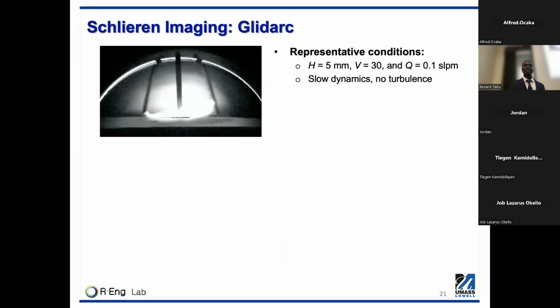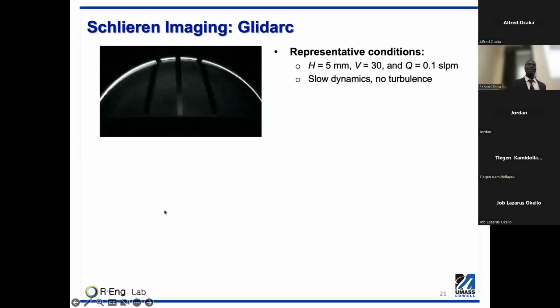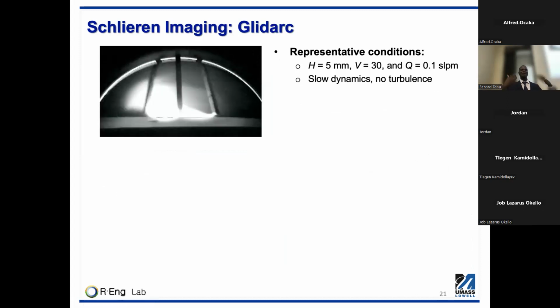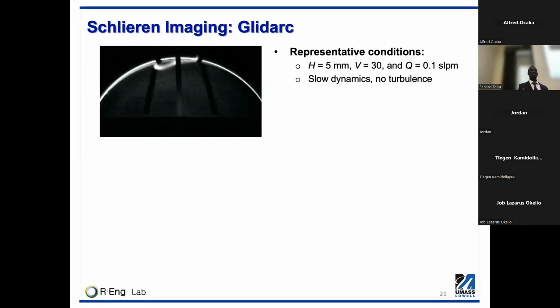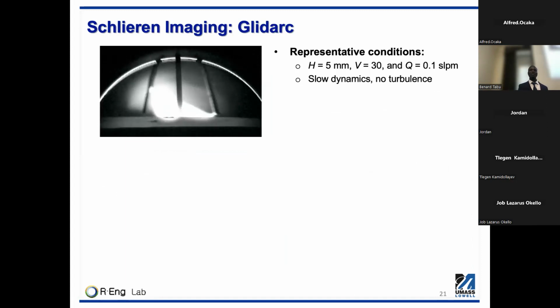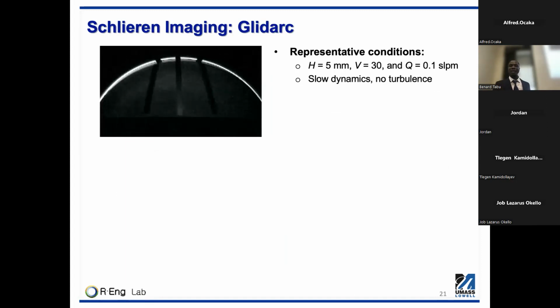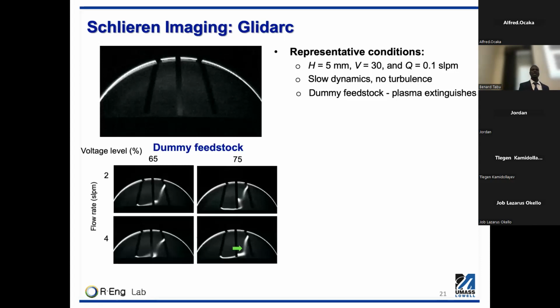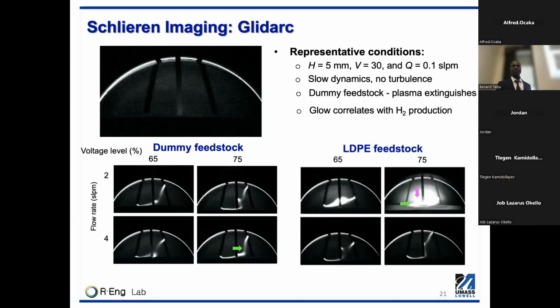Now this is for the glidarc. We had to reduce the frame rate, and for us to see this, the arc glides slowly along the electrodes, and as it impinges onto the feedstock, there is this glow, and we also wanted to see the correlation of this glow with the hydrogen production. For the dummy feedstock, as the arc impinges onto it, the glow extinguishes. The plasma extinguishes without the glow, whereas for the feedstock, the glow is actually more pronounced, and we correlate this to higher hydrogen production.